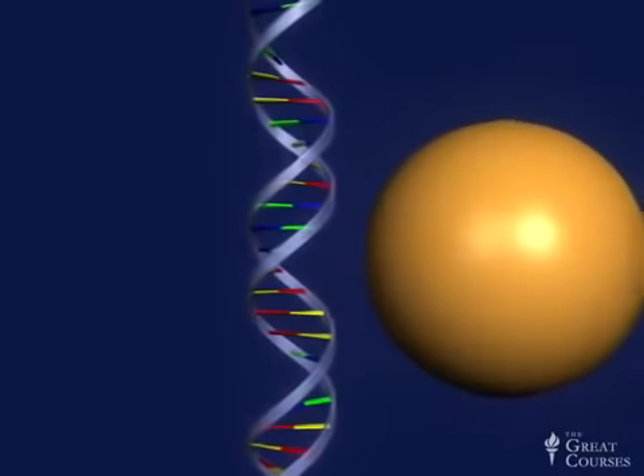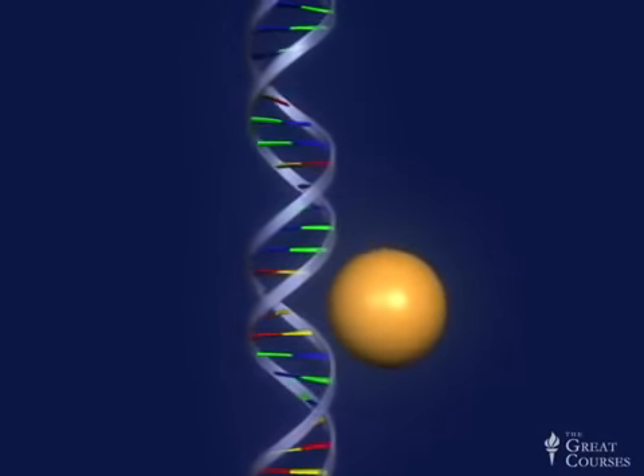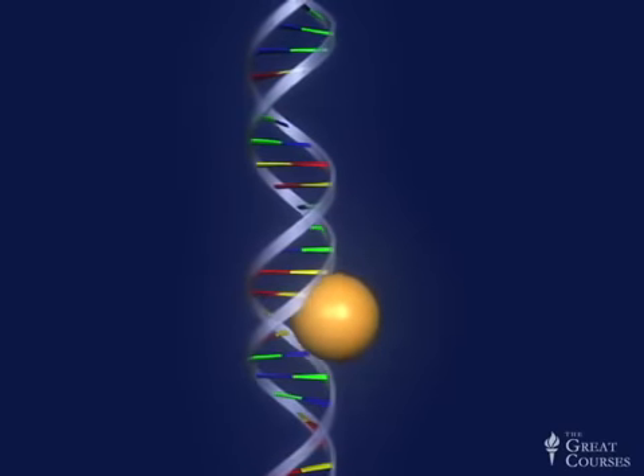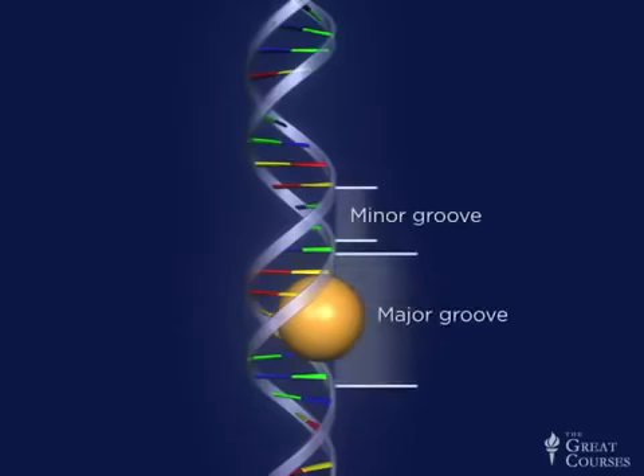Now, why would a bit of heat kill a cell? Well, most biomolecules lose their shape when they're heated up, and this interferes with their ability to function. And in certain cases, gold nanoparticles get really close to molecules. For example, it was discovered several years ago that a 1.4 nanometer gold particle was exactly the right size to sit in the major groove of DNA. You'll remember that the double-stranded structure of DNA contains 2 grooves or spaces between the 2 strands of DNA. And these grooves are actually asymmetric, and the larger one, which is about 2.2 nanometers wide, is referred to as the major groove, while the smaller one, which is about 1.2 nanometers wide, is the minor groove.